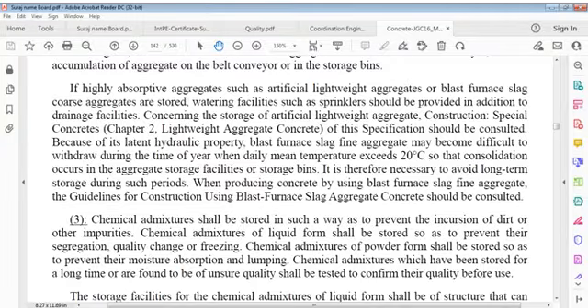Concerning storage of artificial lightweight aggregate, the specs for special concrete, lightweight aggregate concrete should be consulted because of its latent hydraulic property. Blast furnace slag fine aggregate may become difficult to withdraw during the time of year when daily temperature exceeds 20 degrees Celsius, so that consolidation occurs in aggregate storage facilities or storage bins. It's therefore necessary to avoid long term storage during such periods. When producing concrete by using blast furnace slag fine aggregate, guidelines must be followed.